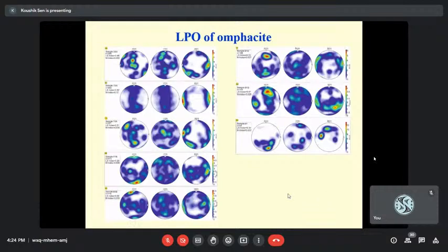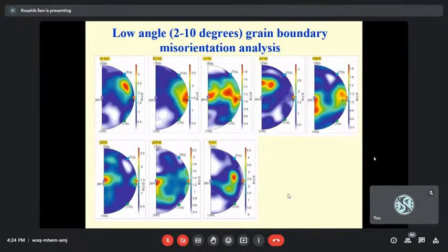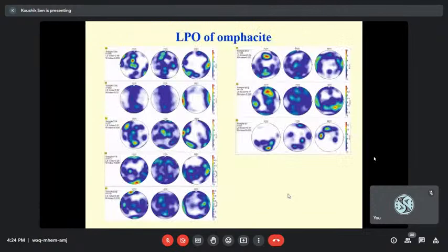It doesn't give any meaningful inferences. So we can see the type 1, the 7X, that is typically showing the L-type fabric. And for type 2, it transitions from LS to some to S-type. But type 3 doesn't really have any meaningful lattice preferred orientation. Then some of the samples are giving us a mixed kind of signals like LS and SL, and some don't really give us any kind of signals.